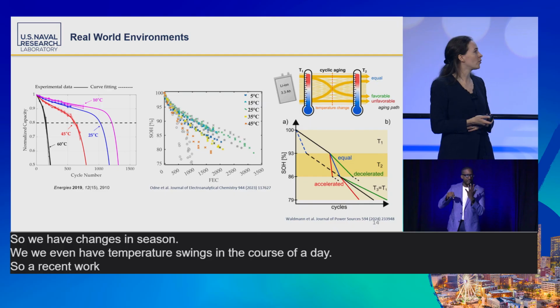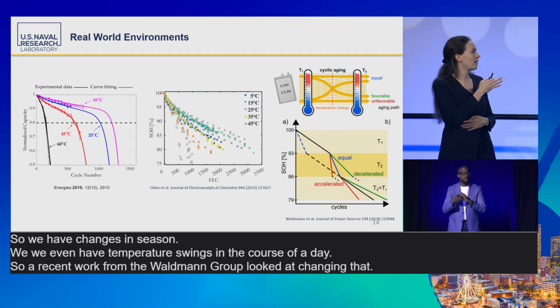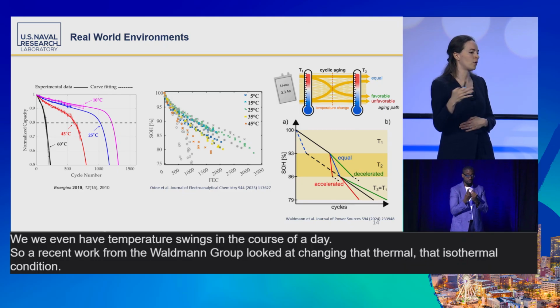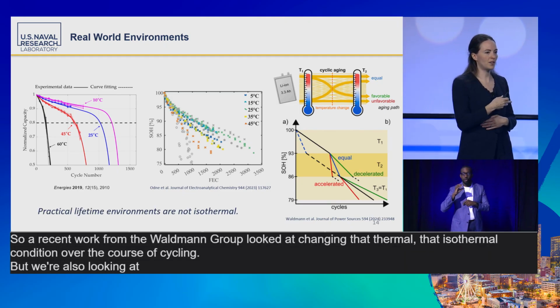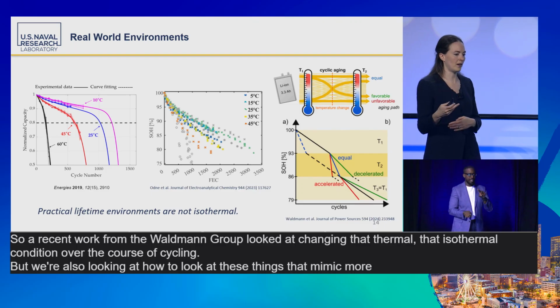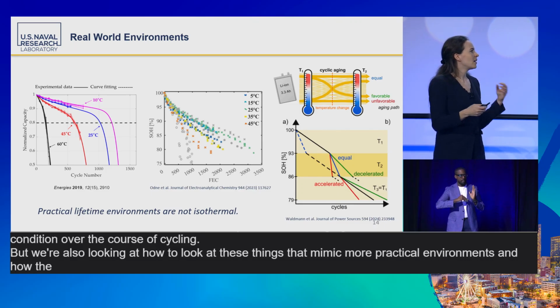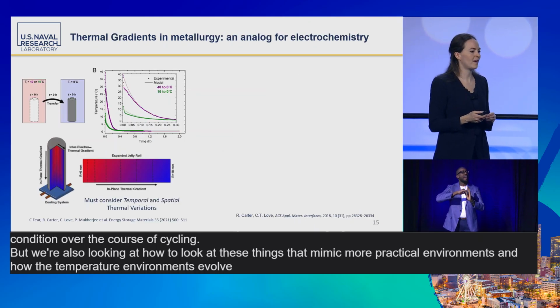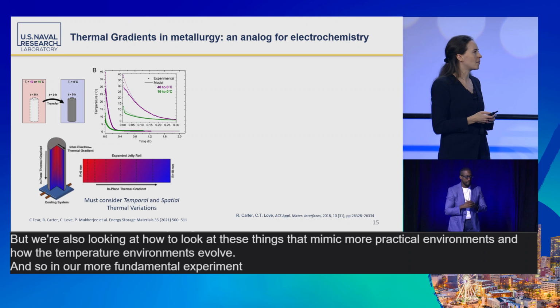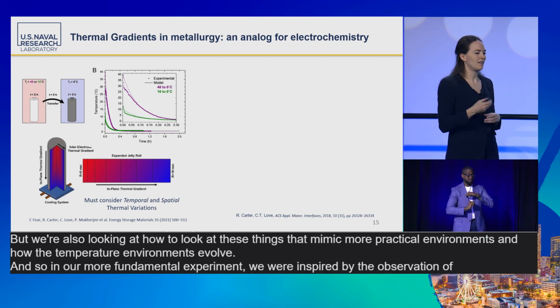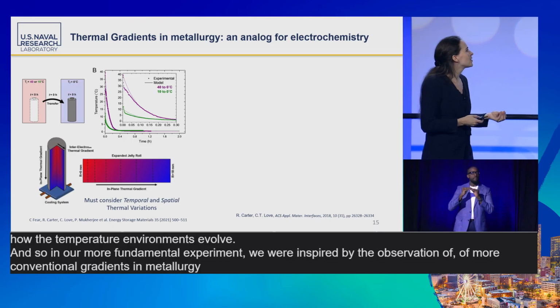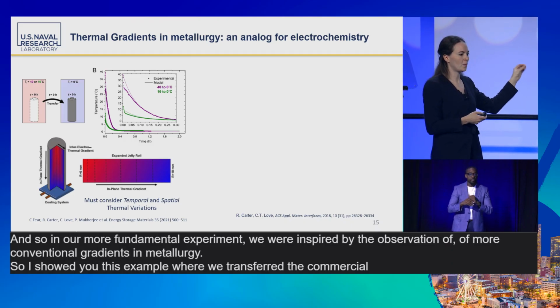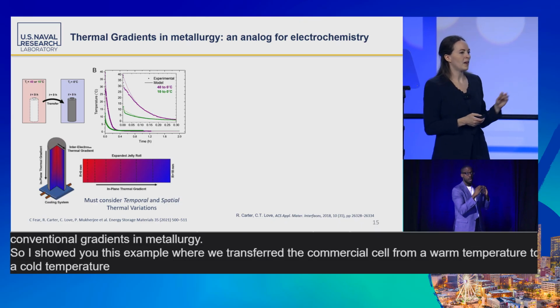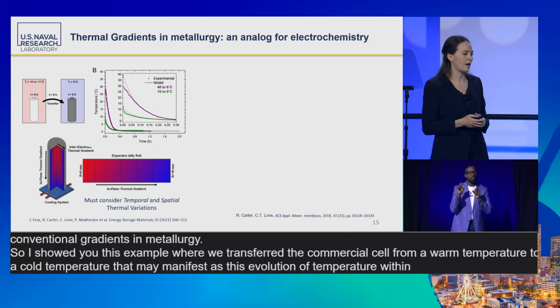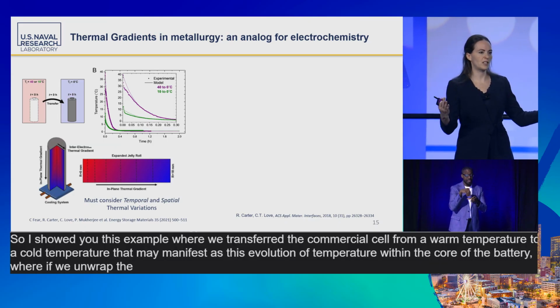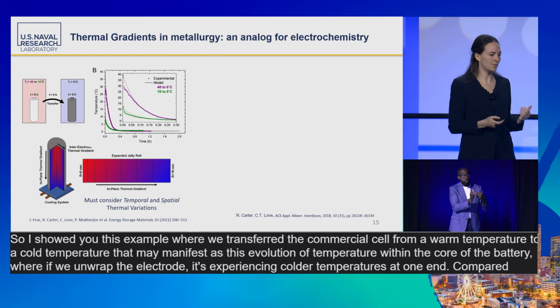A recent work from the Waldman group looked at changing that isothermal condition over the course of cycling. But we're also looking at how to mimic more practical environments and how the temperature environments evolve. In our more fundamental experiment, we were inspired by the observation of thermal gradients in metallurgy. I showed you this example where we transferred the commercial cell from a warm temperature to a cold temperature. That may manifest as this evolution of temperature within the core of the battery, where if we unwrap the electrode, it's experiencing colder temperatures at one end compared to the other.